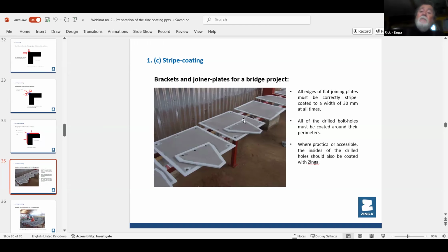Every single one was stripe coated, and then the next day the guy came with a spray gun and just sprayed on the full coat and covered them. So instead of doing them individually, you put them together, and he sprayed like 10 at a time, so it was quite fast. And when you spray them, you can also brush and roll the coating on, as long as it overlaps the stripe coating. Then you have an unbroken film of galvanizing over the entire surface. So there are no weak areas at all. There are no thin areas. Everything's thick and solid all the way around. So each one of those panels was fully galvanized. And we said to the bridge owners, this will be there for the next easy 30, 40 years, easy, because of that.